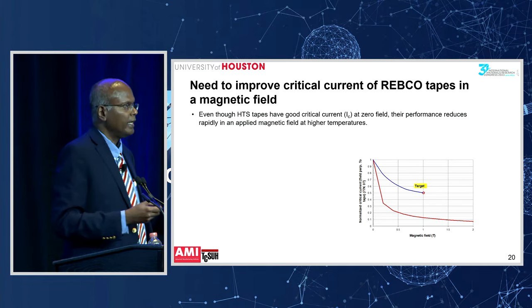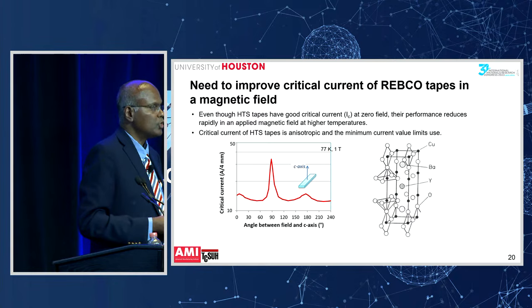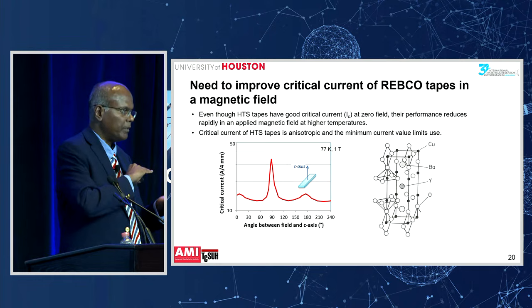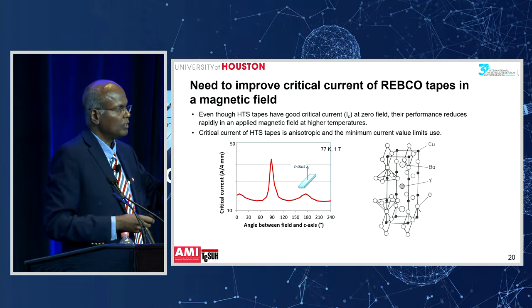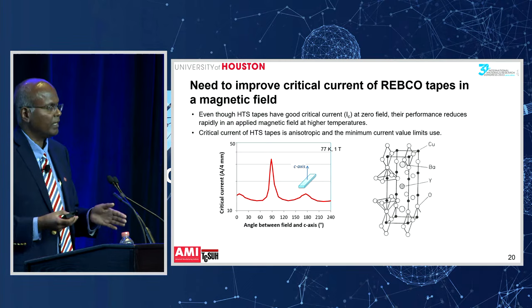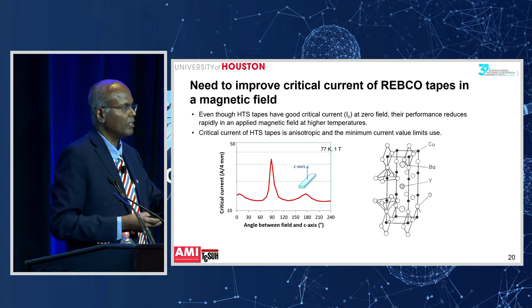So we really cannot use it in any kind of magnetic field application. And also, you can see this material is quite anisotropic. So what happens is, if you apply a magnetic field along the tape direction, parallel to the tape direction, you can carry good current. But once you move the magnetic field away from the tape direction, and in a lot of magnetic field applications, the field is perpendicular to the tape direction, the current carrying capacity drops off quite rapidly.